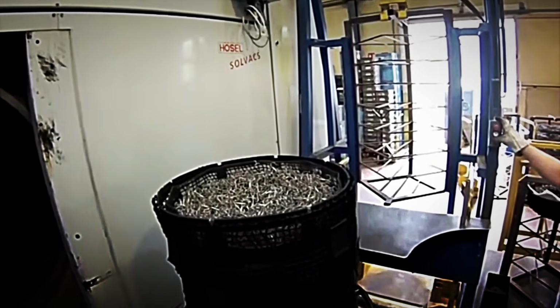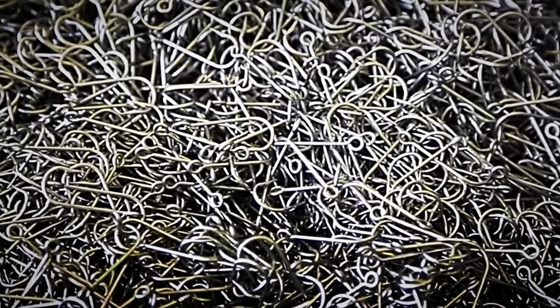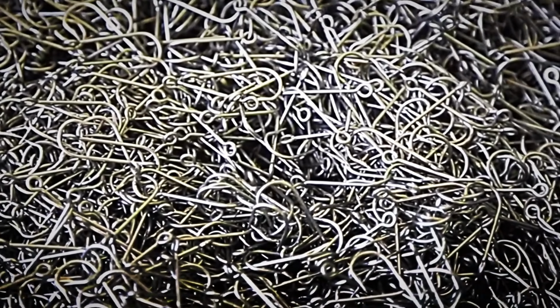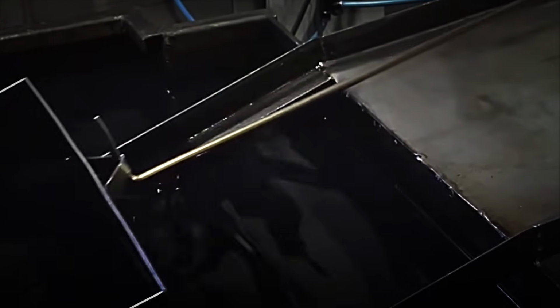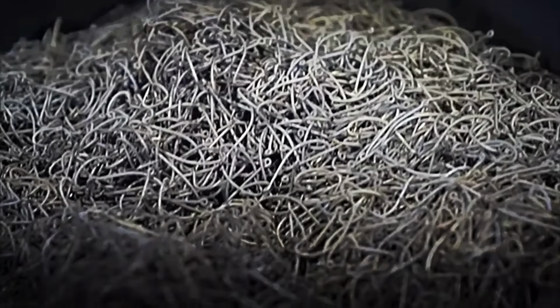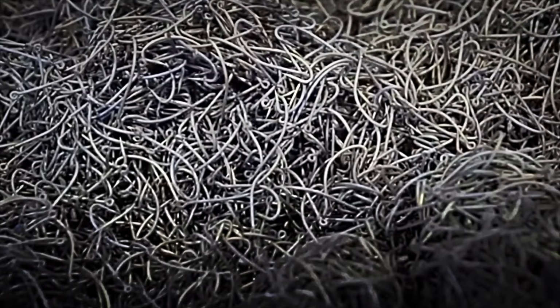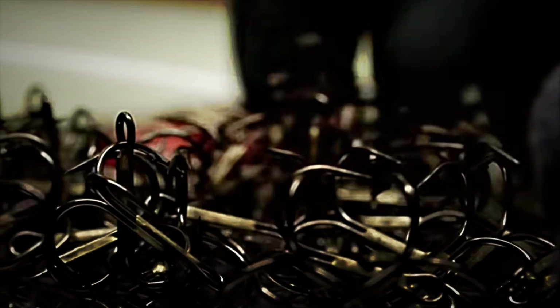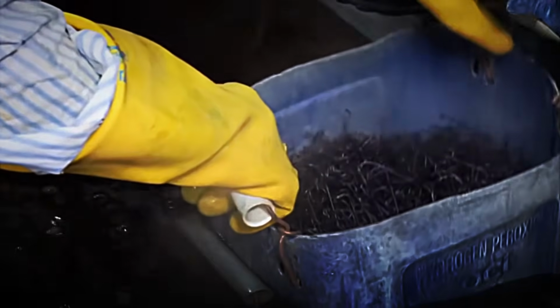However, steel that is too hard can become brittle. To prevent the hook from breaking under tension, a second treatment known as tempering is applied. During this stage, the hooks are reheated to a lower temperature, which releases accumulated internal stresses and restores some elasticity to the metal without sacrificing strength. After completing these thermal cycles, the hooks undergo a cleaning process to remove oils, residues, and particles that may have adhered during heating. The next phase is surface finishing.